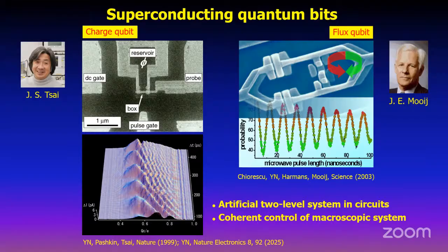So this is again a similar Cooper pair box, with a small aluminum island connected to the reservoir electrode through a Josephson junction. This is just a discrete Josephson junction. By applying a very fast, 100 picosecond scale voltage pulse to control the chemical potential of this island, we dynamically change the relative energy between the 0 state and 1 state, and use the coherent oscillations when we suddenly make them degenerate and they start to oscillate between the two. And then after the pulse, it was kind of frozen. So that's what we saw in this device as a function of time. And then you see clear oscillations between these two states.